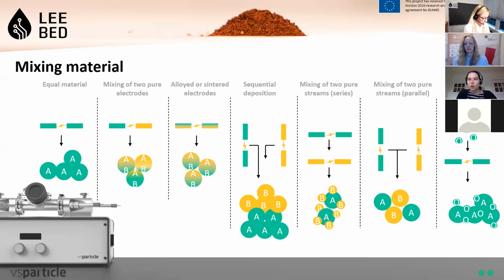You can also put the two generators in series to dress the particles of material A with nanoparticles of material B, like core shell particles. And you can also adjust the gas that you use. For instance, you can use oxygen or small quantities of oxygen in your carrier gas to produce metal oxides.